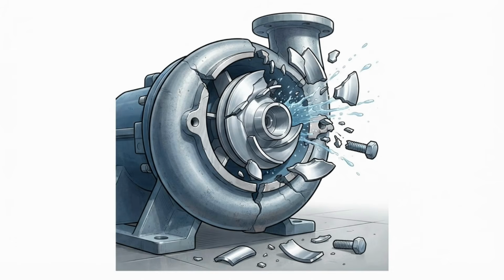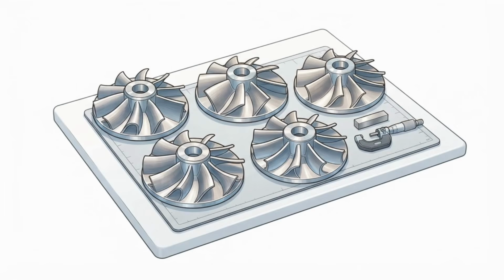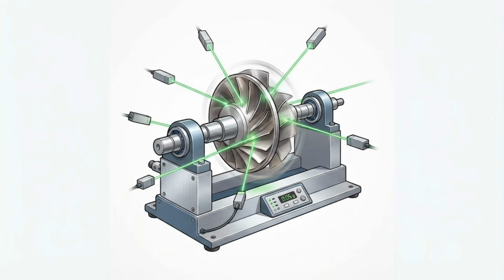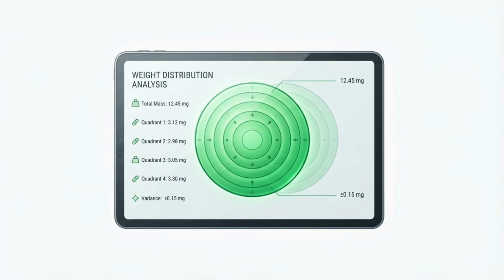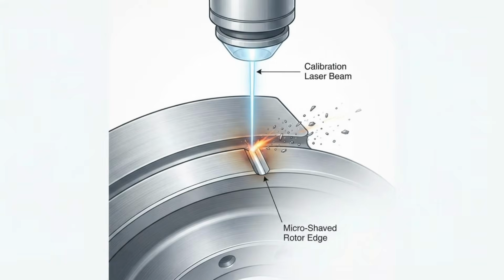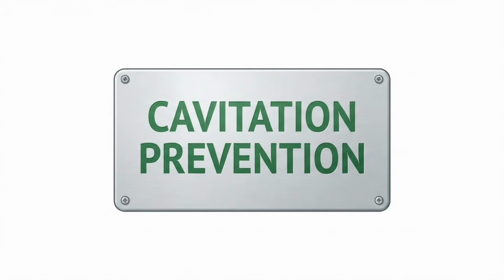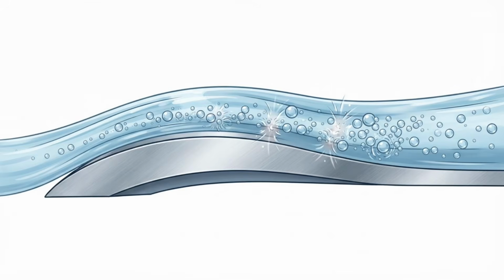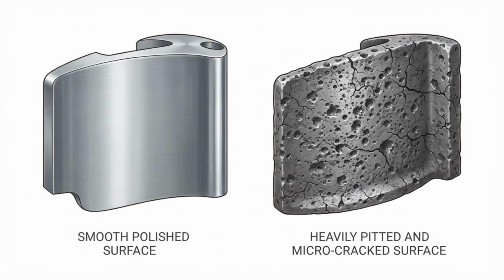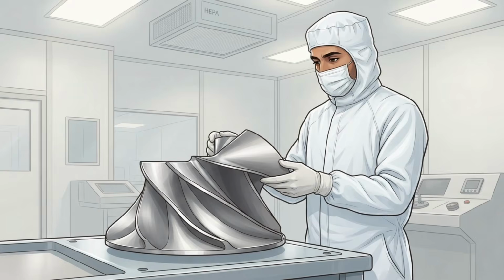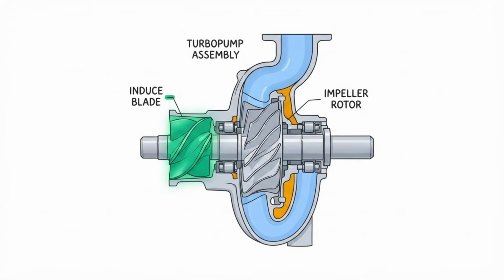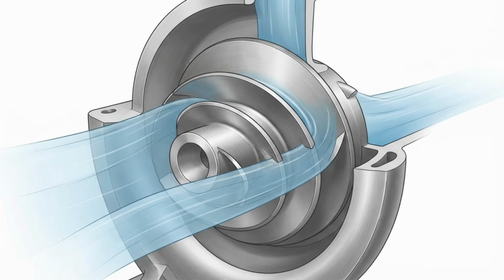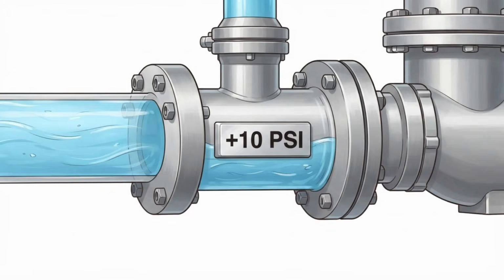Therefore, the completed rotors undergo dynamic balancing on specialized machines that precisely measure and correct their mass distribution at microscopic levels. To prevent cavitation, the rapid formation and collapse of vapor bubbles that can pit and destroy the metal pump blades, engineers manufacture inducer blades that sit just ahead of the main impeller. These corkscrew-like blades gently grab the low-pressure liquid and slightly pressurize it before it hits the violent main pump.